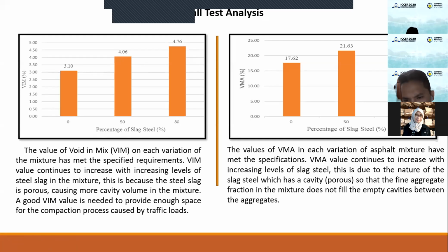Steel slag has a porous capacity, so the fine aggregate fraction in the mixture does not fill the empty voids between the aggregate.